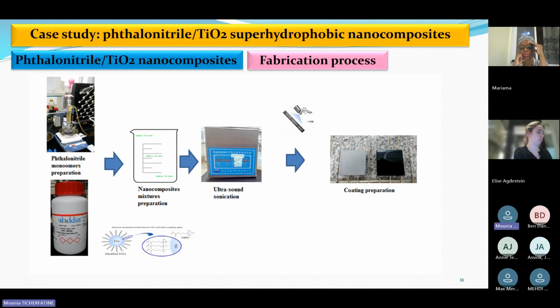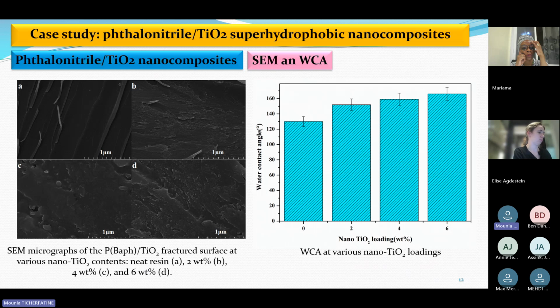Scanning electron microscopy was used to study the morphology of the coating. In Figure A, the unfilled resin shows a smooth and featureless surface morphology. On the other hand, adding the silane-treated titanium nanoparticles caused an increase in the surface roughness, for all nanoparticle loadings shown in figures B, C, and D. The WCA measurement confirmed that all nanocomposites had values over 150 degrees and were all deemed superhydrophobic.